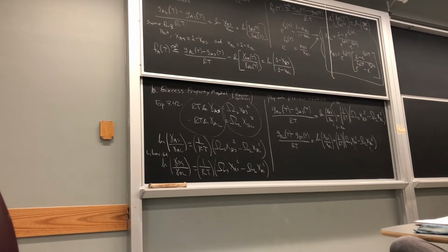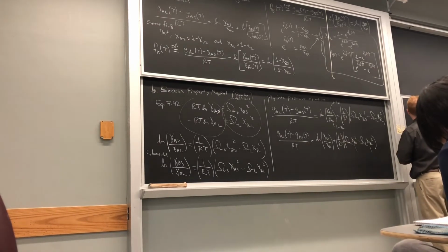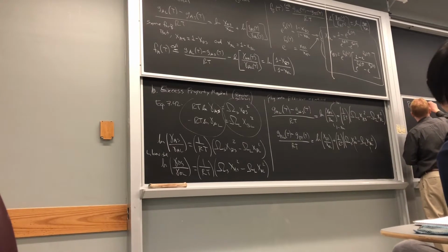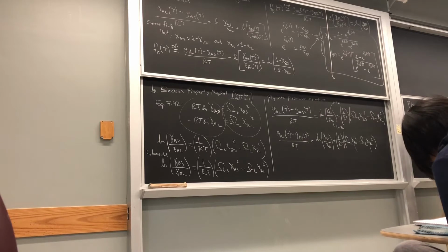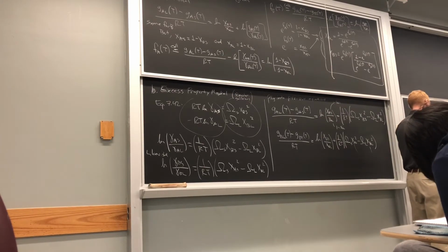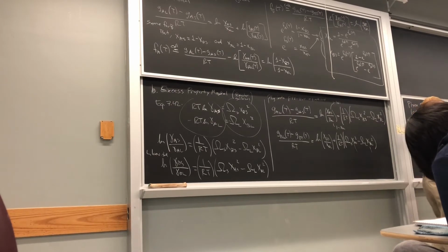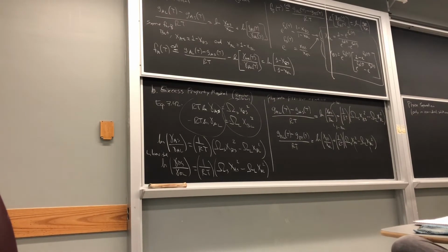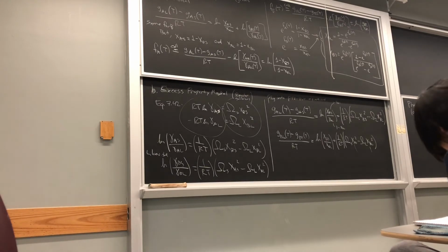We're going to talk about phase separation. It happens only in non-ideal solutions. It's not going to happen in your ideal solutions. What happens with phase separation is that the attraction between like molecules, that is A and A, or B and B, is stronger than the attraction between dissimilar molecules A and B, below a certain critical temperature.